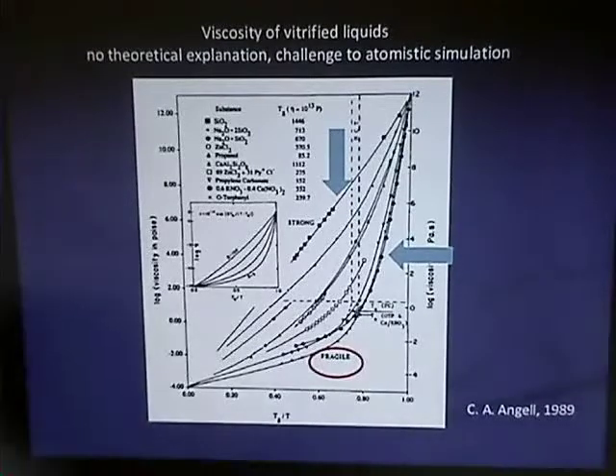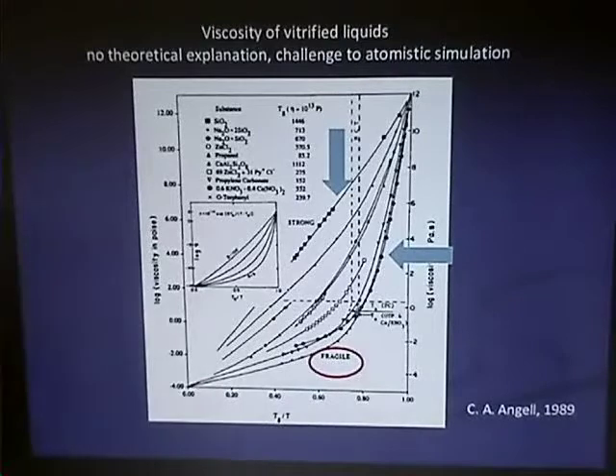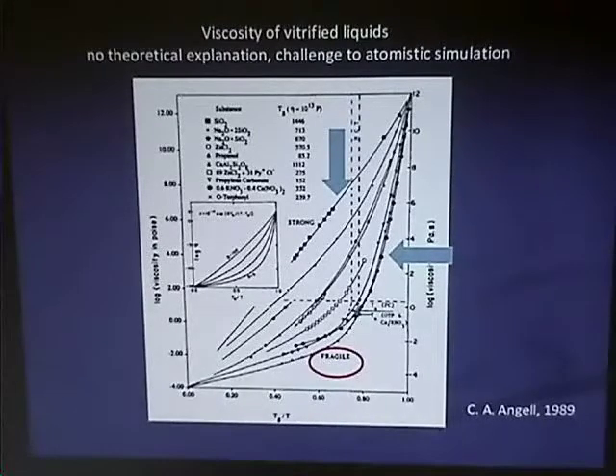Where is the audience in total? Dürr recently challenged this Vogel-Tammann law in a paper, right? And he said it's all wrong because it doesn't fit very well - it's a good approximation, but it's wrong in the detail. Is that something we all agree on? No, I have a big issue. He was making a big deal out of the fact that if you extrapolate, it doesn't really diverge. But if you constrain yourself to temperatures above TG, there's no issue.